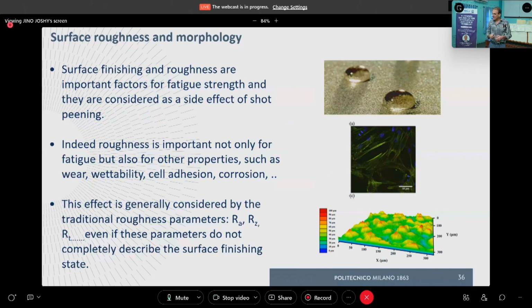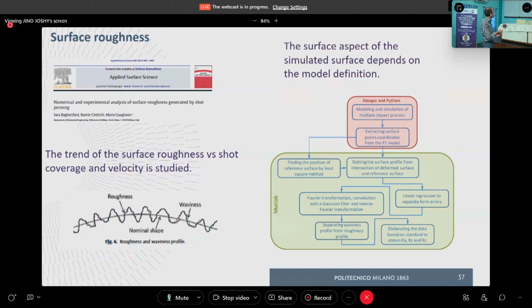Okay, and now let's see what we have done about surface finishing, surface roughness. Indeed, the first thing we have done is to develop a finite element model oriented, aimed not only to residual stress calculation, determination, estimation, but also to the estimation of the expected surface roughness. This is much more intriguing from some point of view.